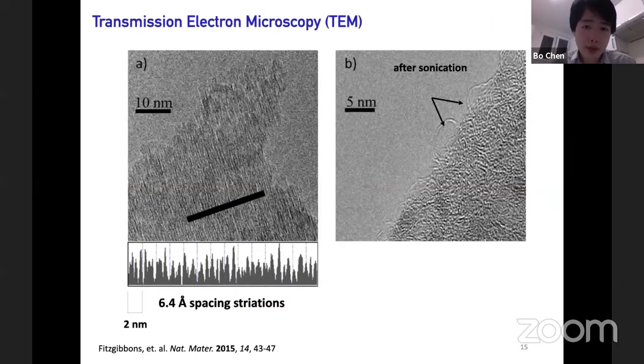Transmission electron microscopy image you see here shows these striations for the sample. And if you follow this black line, you will see the peaks spaced at 6.4 angstrom, which agrees with the X-ray diffraction, also with the simulation. So when you sonicate the sample in a solvent to break apart the thread, you will be able to see individual threads protruding out from the edge of this big sample.